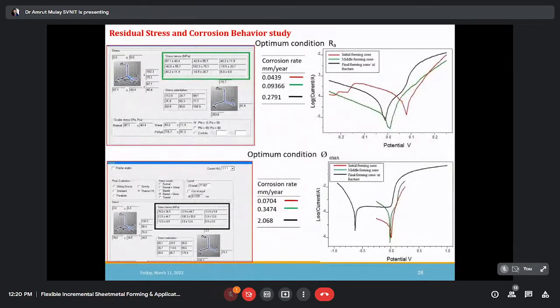residual stresses. Now here you can see that the residual stresses are increasing, 0.0439. It means that there is very little residual stress at the initial forming, but in the middle of forming it slightly increases, and at the end it is increased much, right? So now you can see this is the difference. So we can say that the residual stress in the material, because residual stress is nothing but a compressive stress, because ultimately you're compressing the component, right? So the residual stress has a very significant effect on the corrosion resistance.